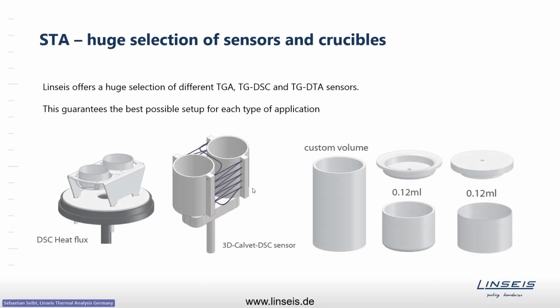Not only the furnace is a very flexible optional part, but also the sensors. Speaking about the TG-DSC combination, we have the typical standard DSC sensor head, a so-called DSC heat flux sensor, which is basically a ceramic rod with a ceramic disc containing a metal sensor head, which has space for 2 crucibles. These crucibles are made out of aluminum oxide, aluminum, gold, platinum, quartz, sapphire, graphite, whatever you need. Again, the crucible material depends on what kind of sample you want to measure and what temperature range you have. They all fit into the standard DSC head.